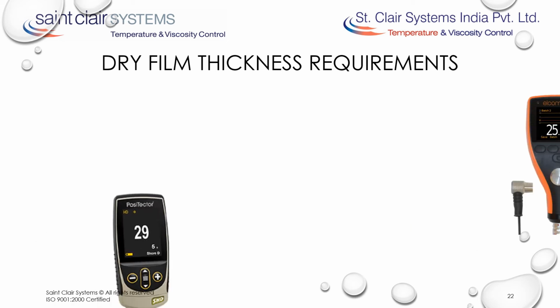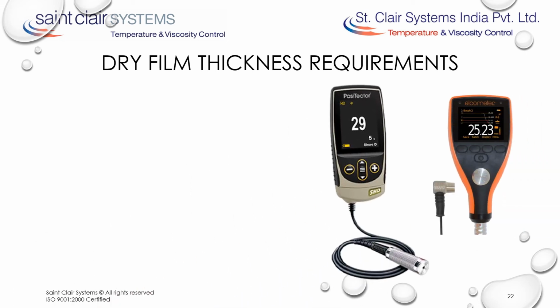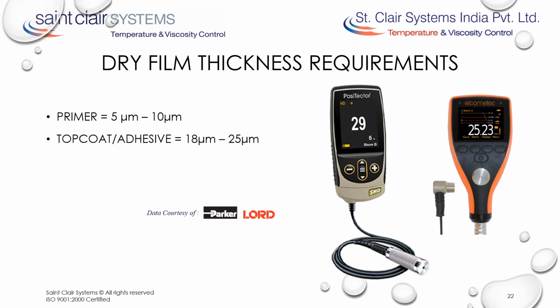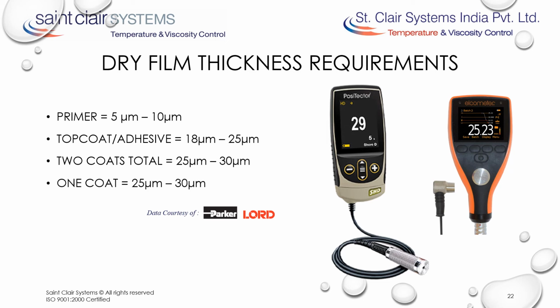First, we have to start by establishing our dry film thickness range. Per data provided by Parker Lord, primers should be applied at a 5 to 10 micron dry film thickness. The top coat or adhesive should then be applied at an 18 to 25 micron dry film thickness, for a total dry film of 25 to 30 microns. Likewise, a single coat application should be in the 25 to 30 micron dry film range.